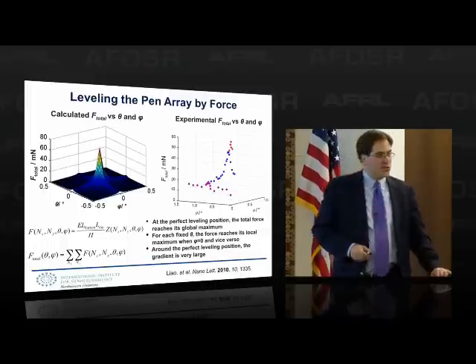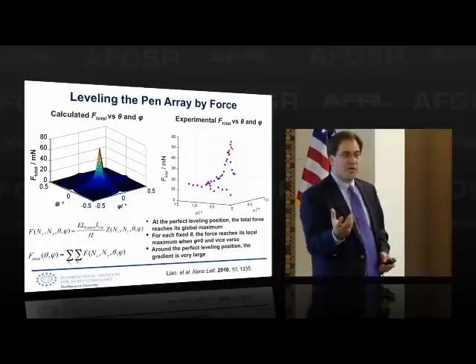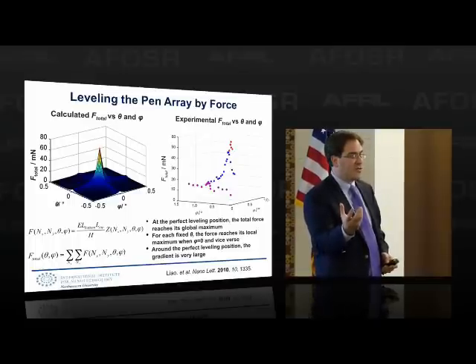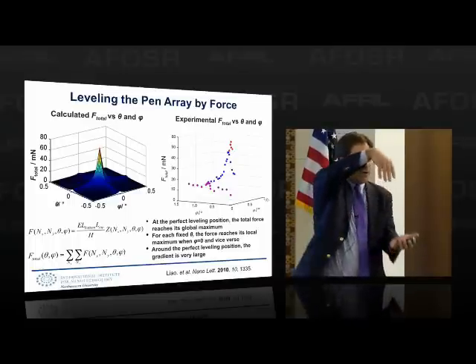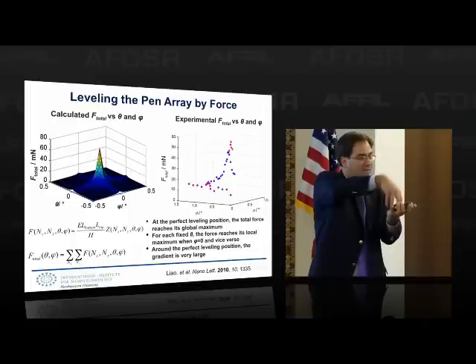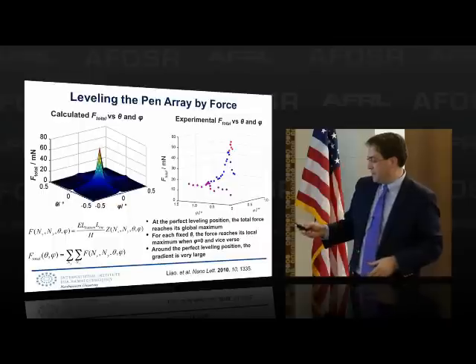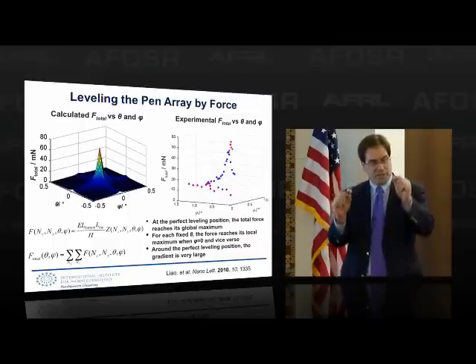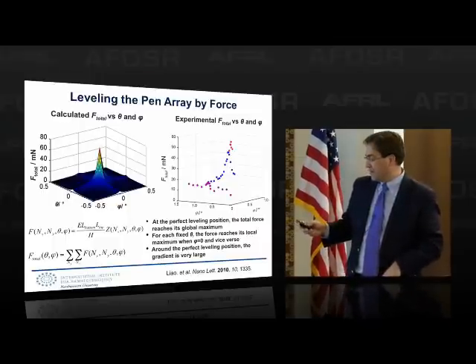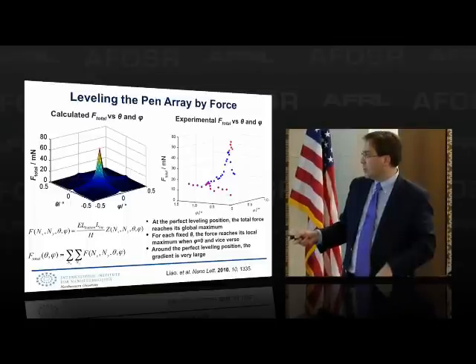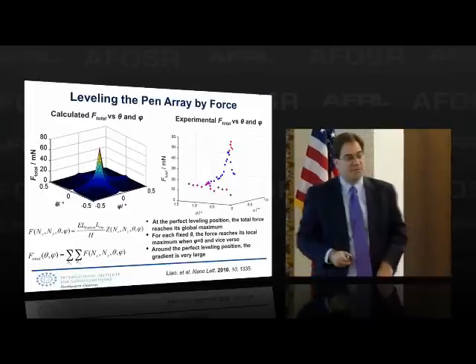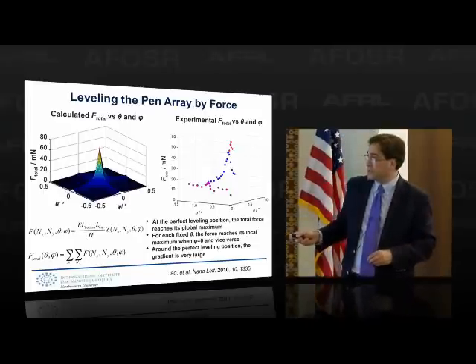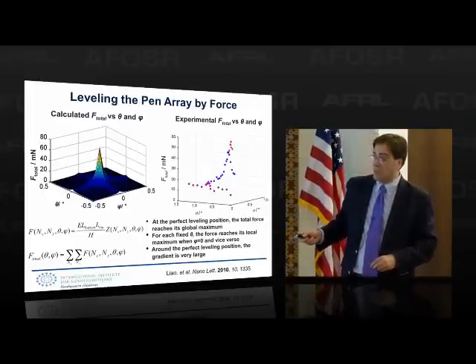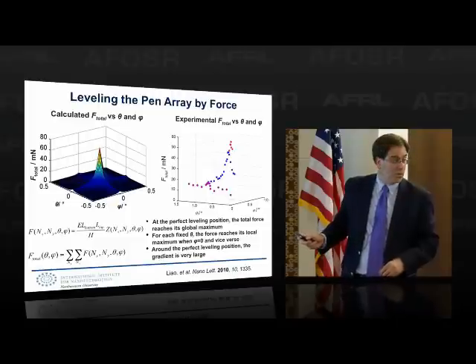And so we said if that's true, then what we could do is put an ordinary scale, a balance, underneath the substrate holder, and then just use the balance to measure the effect of the contact force with the substrate. And then we could tweak with screws that adjust the tilt, theta and phi. If you look at this, here we're zeroing in on theta, we adjust, and all of a sudden we see a local maximum in terms of contact force. This is modeling over here, this is real data. This is not the global maximum that we modeled over here. This is what we'll call a local maximum.